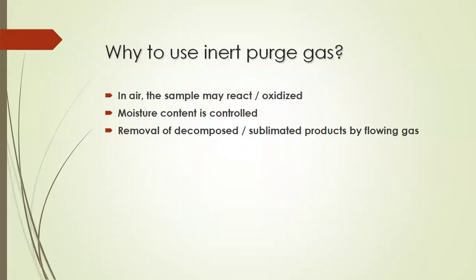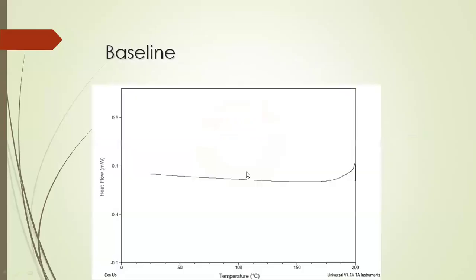Always use an inert purge gas. Why inert? Because in air, your sample may react or oxidize, and you have seen in TGA the effect of your sample oxidizing or reacting with the purge gas. In DSC also you get similar types of reactions with the purge gas. So avoid that and use an inert gas. Again, suppose you are purging your instrument with air. Air also contains some percentage of moisture. Commercial air cylinders, or air from a compressor, always contain some moisture. Even with good quality filters, getting dry air is a difficult task. And the purge gas can also remove decomposed and sublimated products.